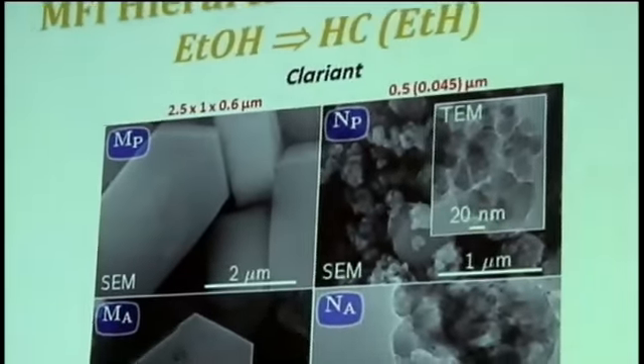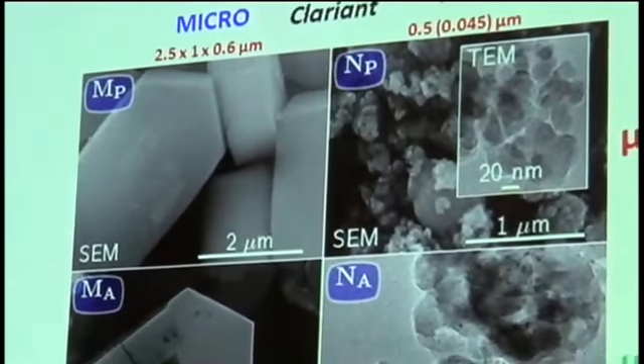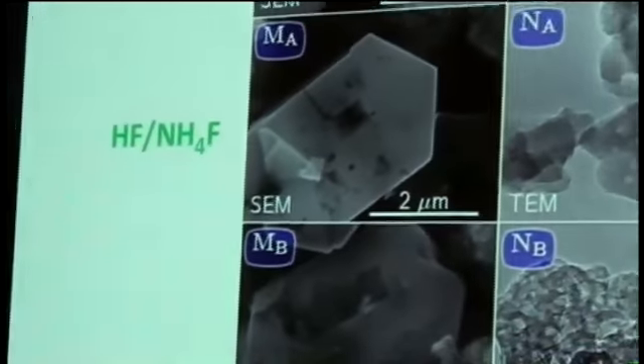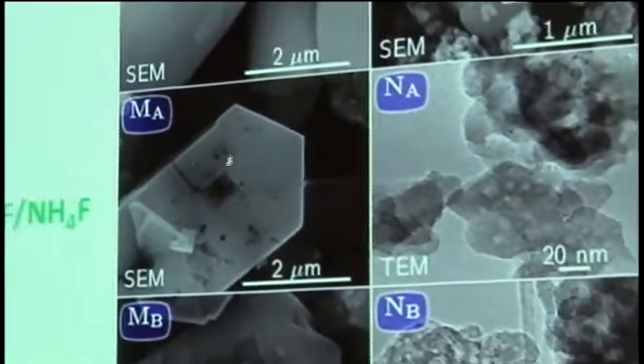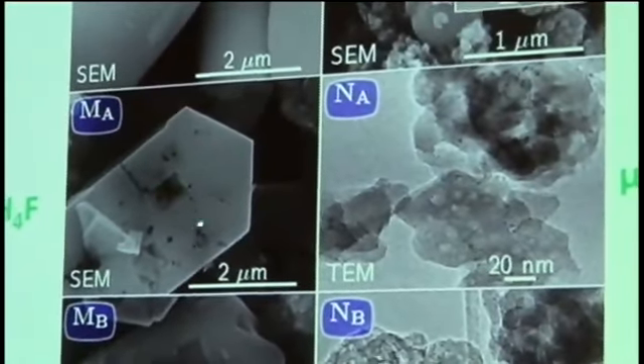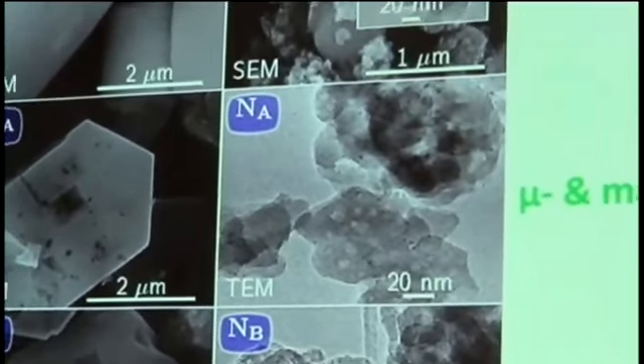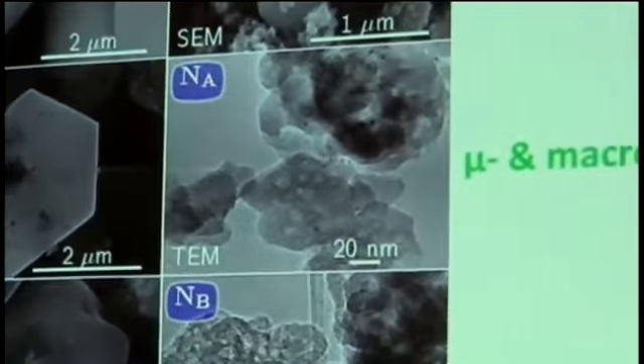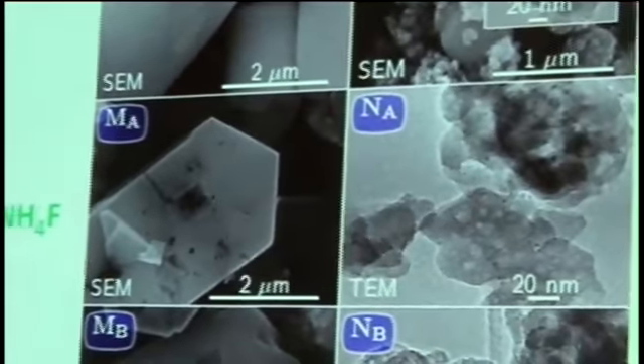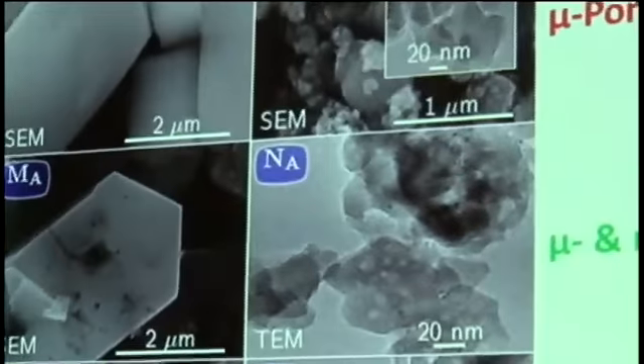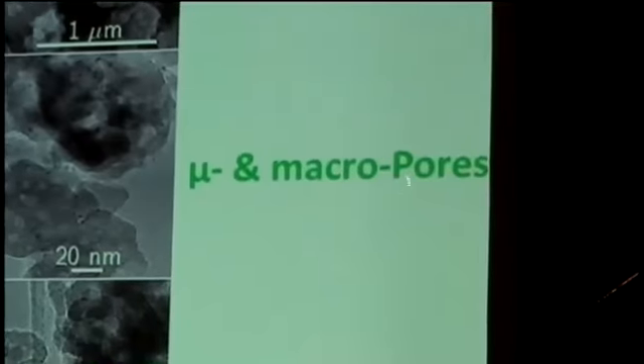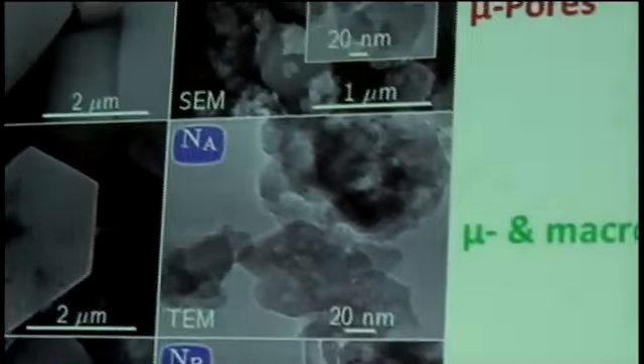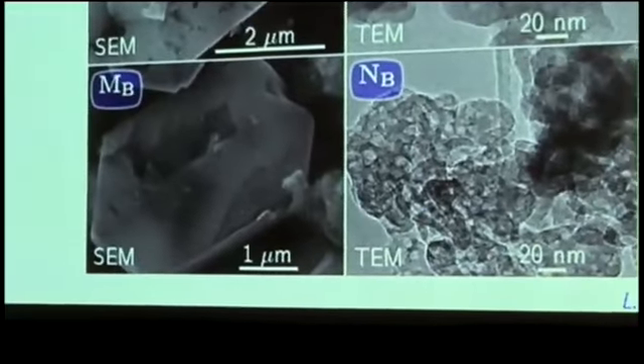Okay? So this material basically here contains only micropores. The material here is what I described before. It's a fluoride treatment where the chemistry of the treatment is relatively complex, but you see that on this material, if you do a fluoride treatment, you start to dissolve part of the crystal, you dissolve all the weak points, but it's a very homogeneous process. So there is a very homogeneous distribution of the fluoride ions, and they do a relatively even job. But what they leave behind are mostly macropores. You can, by fine-tuning, achieve also the level of mesopores.